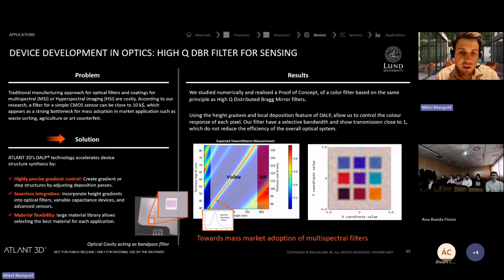This is an interesting use case that even the luxury industry or defense industry can benefit from. When we control the thickness of a certain material like titanium oxide, you change the refractive index, and therefore you change the color of the material. We can control the color because we know the deposition, we control the thickness, we check, and then we are able to print different colors.